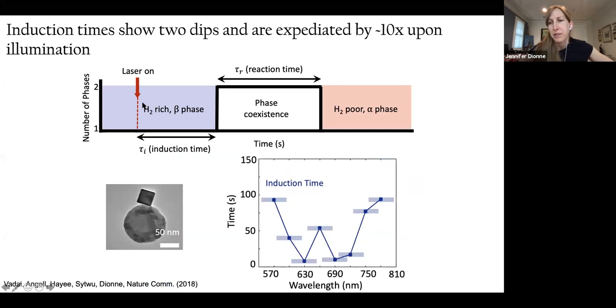So how do these two timescales vary upon illumination? Now we send in different wavelengths, and we see that for wavelengths that are, for this particular sample, roughly in the green and blue and also in the near infrared, the induction time lasts a long time. So essentially nothing really is happening upon illumination when we're at very blue and very red wavelengths. But when we're here in this intermediate regime at wavelengths of, say, 630 nanometers and 690 nanometers, we find that the induction time is extremely short, so less than 10 seconds.